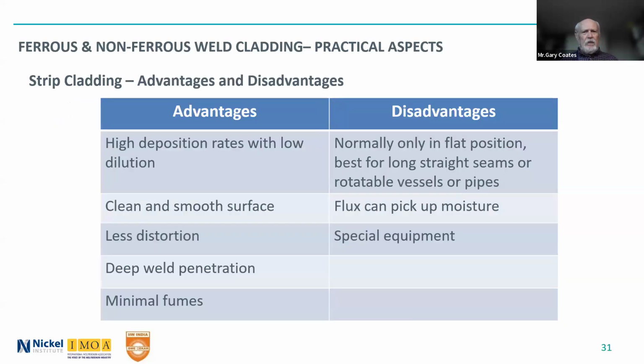So the advantages are high deposition rates with low dilution, and a clean and smooth surface. A weld overlay done by wire will be rippled, and sometimes that needs to be machined smooth in certain cases anyhow. You also get less distortion, deep weld penetration, and minimal fumes. However, strip cladding is only for the flat position. It's best for long, straight seams, and you can use it in rotatable applications. If you can rotate the vessel or a pipe, if it's large enough, you can do that.